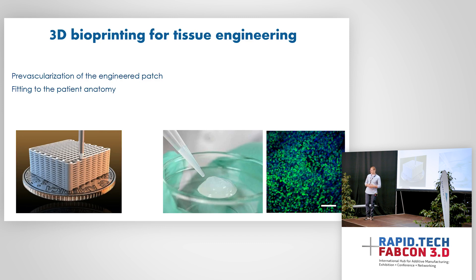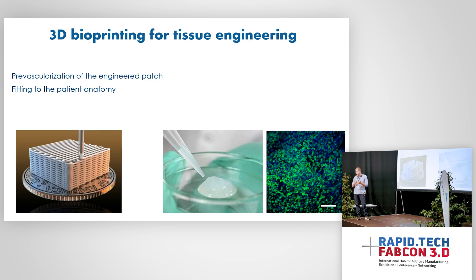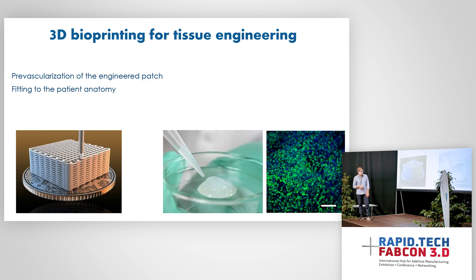A major technology that is arising in this field is bioprinting, which gives answers to both of these challenges — by creating blood vessels inside, and also by printing in the right geometry for the patch. In bioprinting, we print layer by layer, positioning living cells and biomaterials to form this living tissue. However, it has a very constrained environmental framework to work in. Both the materials we use are very soft, and sometimes even completely liquid. And we are incorporating living cells, meaning we need to maintain a temperature between 4 and 37 degrees Celsius, or the cells can simply die.